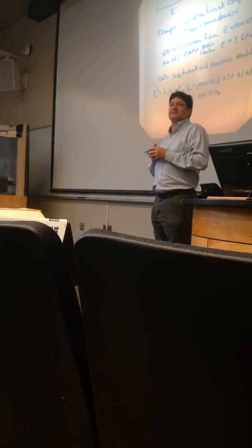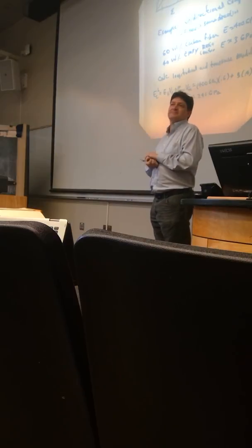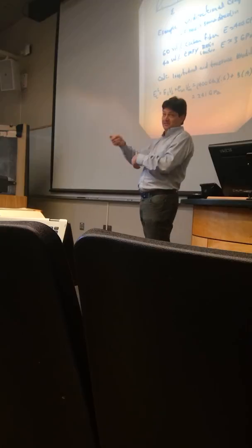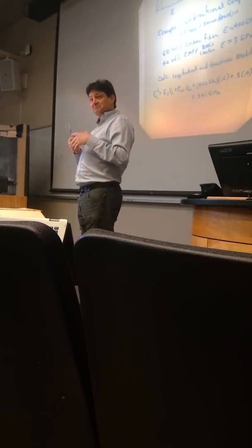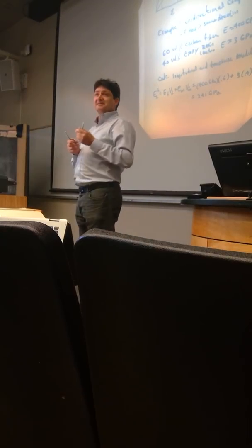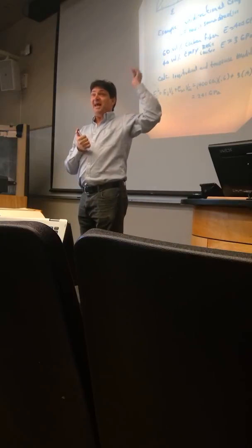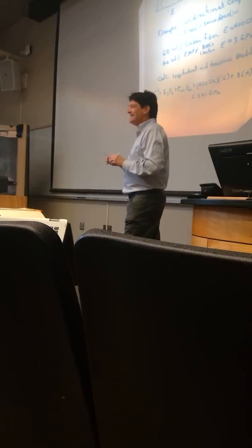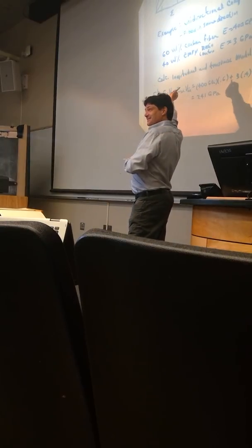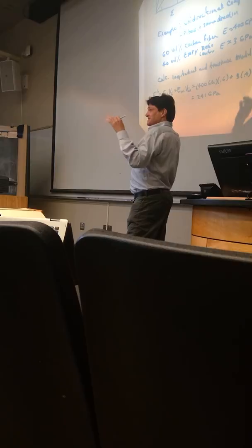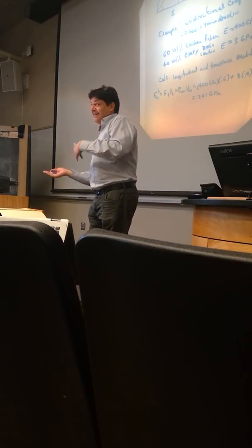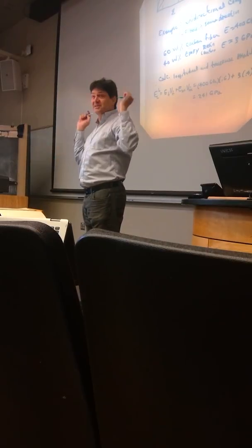The elastic modulus of steel is about 210 gigapascals. So your unidirectional carbon fiber in the direction of the fibers can be stiffer than steel. The density of steel is about 8, and the density of carbon fiber composites is about 2. So if you look at it on a strength to weight ratio, it's 4 times stronger than steel.